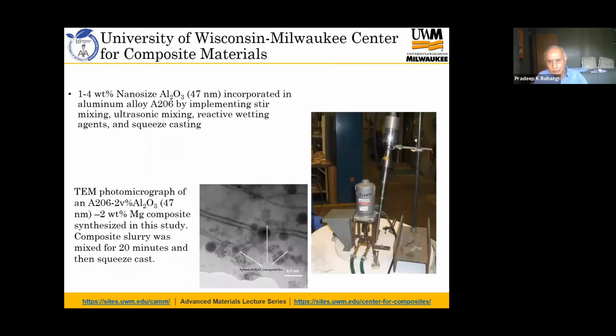And this is a slide from our lab at the University of Wisconsin, Milwaukee, where we are mixing nanoparticles of alumina in a melt of aluminum alloys using a mechanical stirrer as well as an ultrasound energy sonicator. Both these mechanical and ultrasound energies are able to disperse nano-sized particles of alumina, and after solidification, this is a TEM picture. You see 2 volume percentage of alumina particles dispersed in the matrix of aluminum. An example of how, using a simple mixing technique, you are able to produce a nanocomposite.